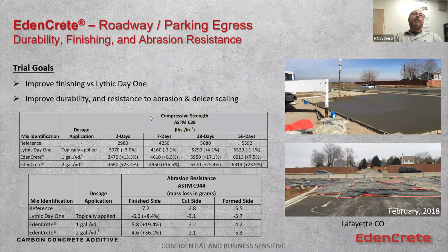So when we look at compressive strength versus the EdenCrete dosage increase, you see what you would expect, right? The Lythic Day One is topical. It does not improve the compressive strength of the full depth of the concrete. When you add EdenCrete, you see the improvements in strength start to go up into double digits.